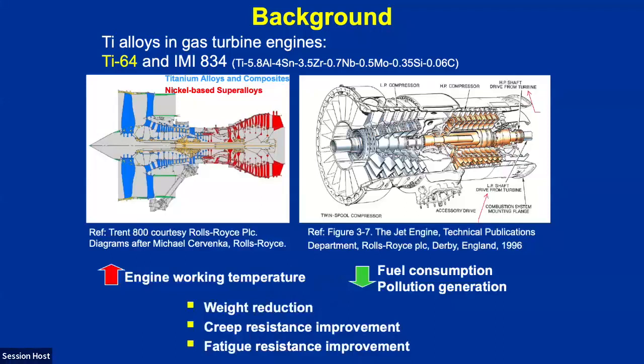As we've heard already this morning, titanium is used quite a bit in industry. And why is titanium used? Weight reduction, creep resistance, fatigue resistance. What we're trying to get at is how we can modify titanium with alloying additions. Boron is a famous inoculant, which reduces the grain size, especially in castings and other processing of titanium alloys. We take advantage of that so we don't have to go through as much raw processing to get the strength and stiffness of titanium increased by adding small amounts of boron.